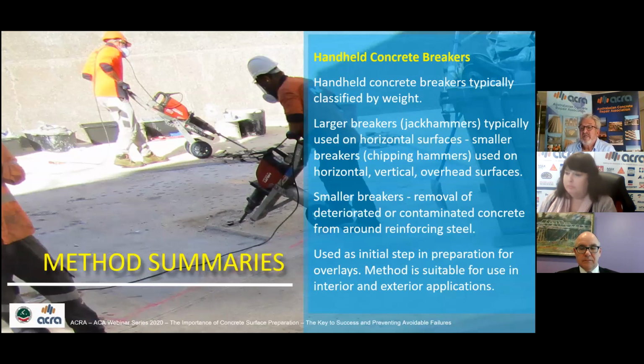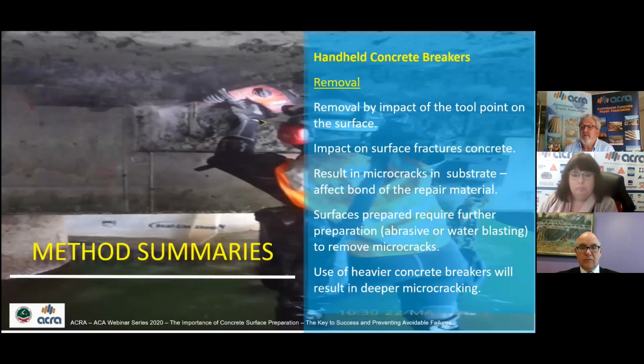14 kilo class jackhammers, and chipping hammers at 9 kilos and under, generally. Surface application of chipping hammers is to remove deteriorated chloride contaminated concrete from around reinforcing. Handheld concrete breakers are also used as a preparation for overlays, as we can see in the slide photo there. Removal is accomplished by the impact of the point chisel with the surface, pneumatic, electric, or hydraulic. The impact of the tool on the surface fractures and splits the concrete, and the surface using chipper hammers or handheld concrete breakers will require further preparation, either sandblasting or water blasting generally, to remove micro cracking.